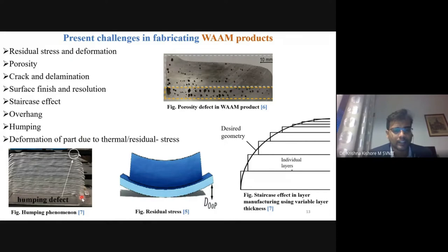So if you assume that the layers are deposited continuously, one layer over the other layer, you can see the depositions are like this. This is the humping effect, right? So this humping effect might be there, and there might be some kind of staircase effect like this. One layer is deposited, the other layer is deposited, and there will be some staircase kind of geometry, like this. This is because of the heat input towards one direction, the heat transfer rate towards that direction, and the movement of the droplet. Once the droplet is transferred to the substrate, because of the viscosity property of this molten droplet, the flowability of the droplet, it will move towards the larger area, right? It will spread actually. Because of this spreading, this kind of staircase effect is also there.